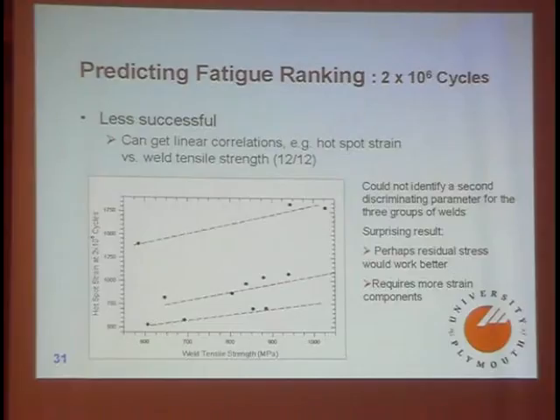It is also possible that we would need more data in the long life regime to establish the slopes of those things better. Because I think below about 1 million cycles, I'm reasonably confident I've got the slope fairly accurately. In the long life regime, I'm less confident that we've got the slope of the fatigue performance accurately. There's not enough data in that. So either the fatigue data is not accurate enough, or probably residual stress will work better. But we have half of the result. We can at least put all the data onto a series of straight lines, and we need another discriminating parameter to sort it out.